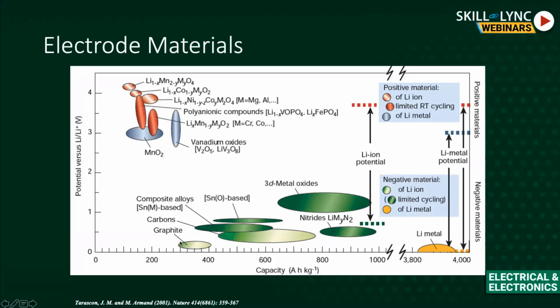And so we commercially use graphite as a negative material. If you look at it, graphite is used because it has a potential that is very close to lithium metal, very close to 0 volts. So your lithium ion acceptor must be as close as possible to lithium metal, and the lithium ion source, which is the positive material, should be as far away from lithium metal as possible. The most ideal situation would be to have a material that is much higher up here, paired with an anode which is as close as possible to lithium metal. And that is why in commercial systems, in all electric vehicles and all consumer electronics, we pick lithium cobalt oxide as our most common cathode material and graphite as the most common anode material.